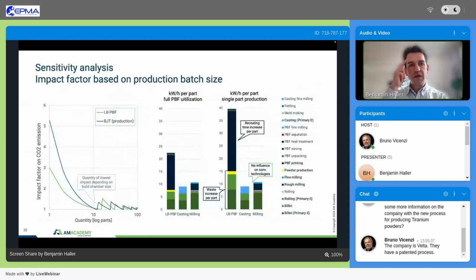So first of all, looking at the production batch size, in directed energy deposition you always produce individual parts, so it doesn't make a difference. But as you can see here on the left side, for laser powder bed fusion, and for a relatively large binder jetting system, when you produce one part you have 3 to over 5 times higher CO2 emissions as compared to when you use a fully utilized build job.